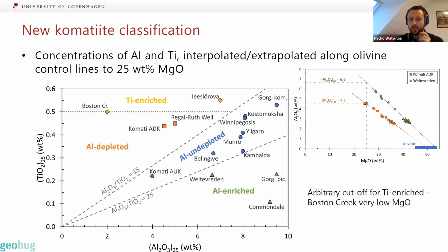25% magnesium. It's important to note that with some of these titanium-enriched komatiites, which are actually quite low in MgO and probably don't technically meet the definition of komatiite, you get artificially high titanium just because you're projecting it so far back down an olivine control line. So that's the Boston Creek flow that I've mentioned in the slide. The figure on the right is just showing how that interpolation and extrapolation works.